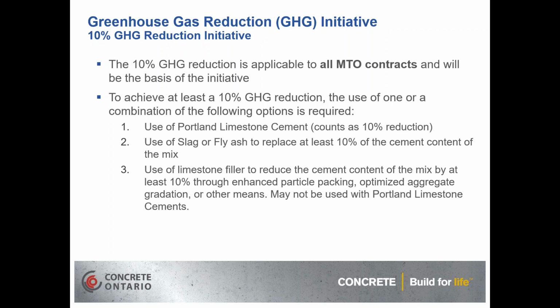following options. One, we can use a Portland limestone cement, and that counts as our 10% greenhouse gas reduction right there. Two, we can use slag or fly ash, at least 10% replacement of the cement content. And again, that will give us our 10% greenhouse gas reduction. We can use a combination of the Portland limestone cement and the slag or fly ash and achieve more, of course, if we want to.